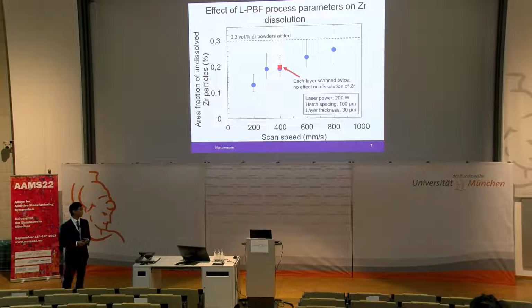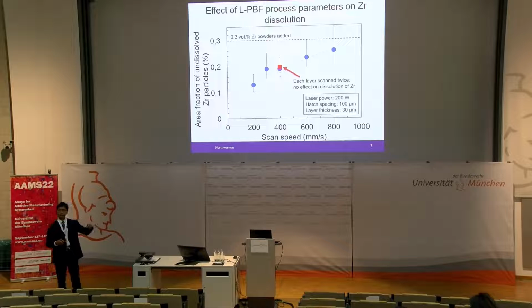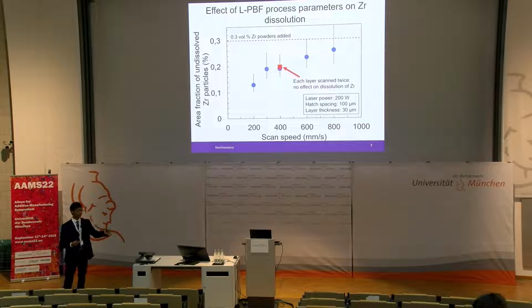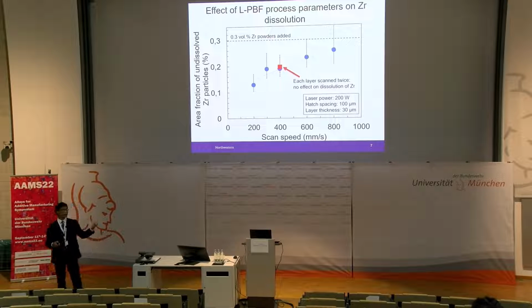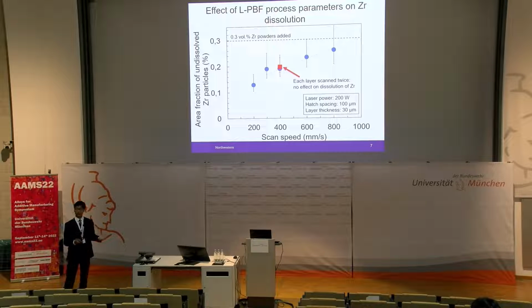Our hypothesis is that the absorptivity of the laser powder bed is changing during the rescanning process. The first time the laser encounters the powder bed, it's encountering a relatively rough surface, so there are multiple reflections that can take place, increasing the amount of energy absorbed. Whereas when the laser is encountering the powder bed for the second time, it's now encountering a more flat surface. More of the laser energy is directed upwards, and the amount of energy absorbed is less. Therefore, it will decrease the amount of zirconium that can be dissolved during the second scan.